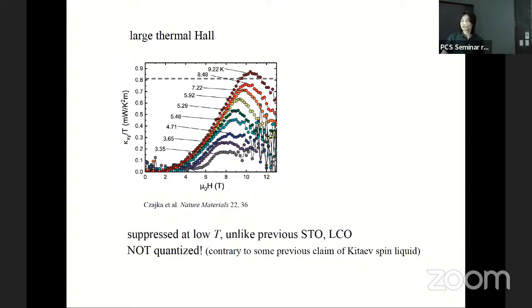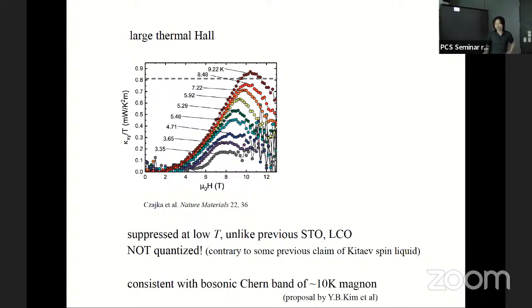Moreover, some early experiments claimed to have observed a half quantized thermal Hall. Now, from this newer data, you can see that it's nothing quantized at all. The early experiment tried to claim something very big, but really it's not, though there was a lot of buzz around. So the puzzle is that it's unlike STO and LCO. It's very large, but maybe a different mechanism. Indeed, the data is consistent with the bosonic Chern band of a 10 Kelvin gap magnon.